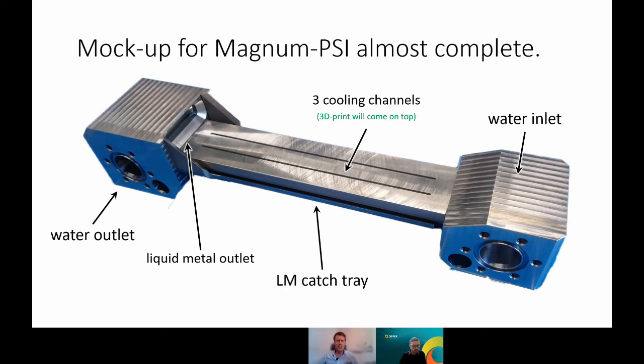So they are, let's say, much more representative of what a disruption would be. There are papers that you can find on how that works with lithium in some kind of porous substrate, not the 3D printed one, unfortunately. And the lithium one seems to perform fairly well. As far as I know, there is no damage as long as you make that substrate out of tungsten and not of anything else. And now the question is, will that work with the 3D printed samples and will it work with liquid tin?